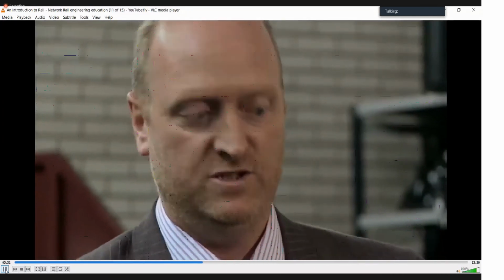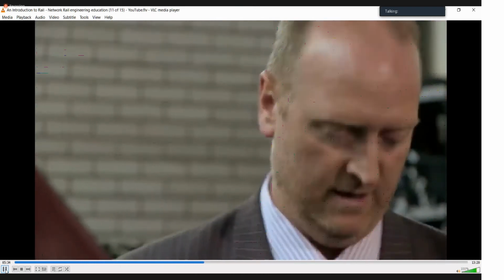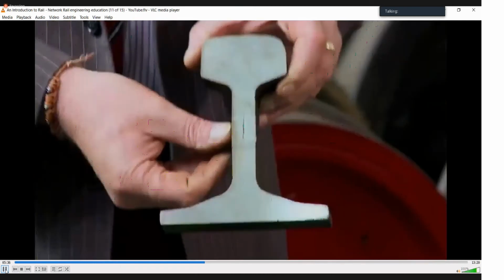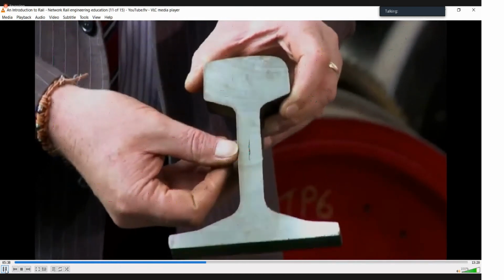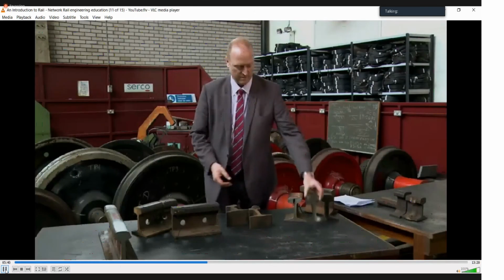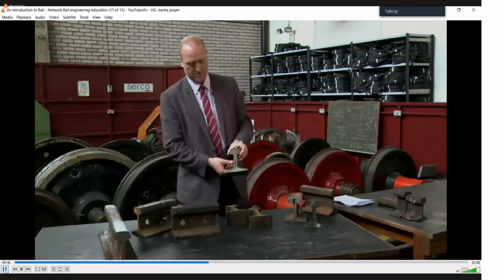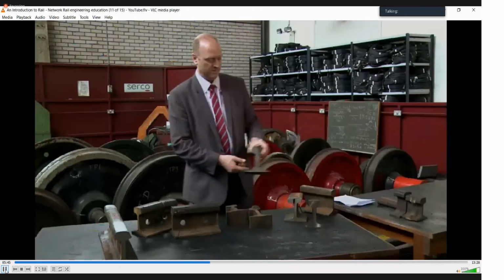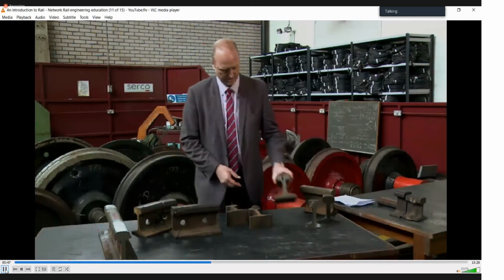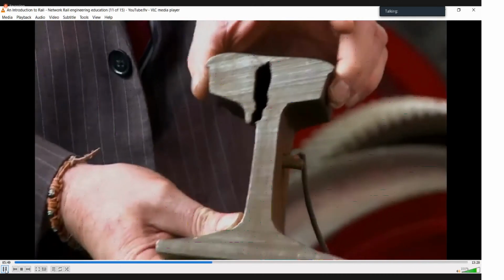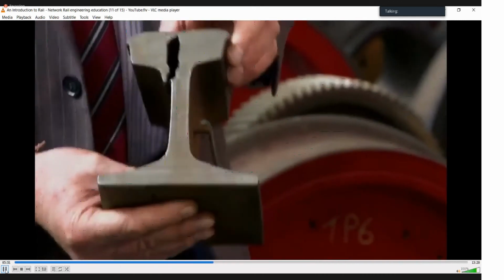Plastic deformation is another thing we see where the rails degrade. This is where the rails are physically deformed. They are spread, the rail steel itself is distorted and deformed under traffic. You can see the start of a small split within the middle of the web. These will propagate under traffic if not managed. They will grow to a larger size, the split will open up, and in extreme cases can result in a piece of the rail becoming detached.